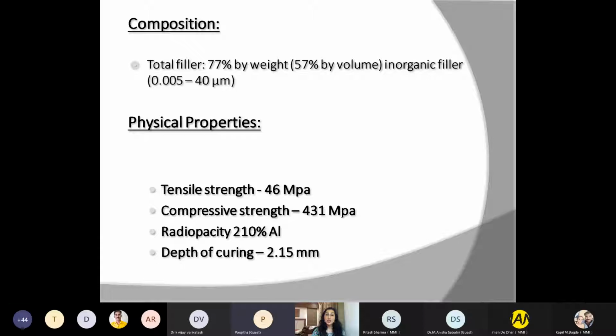The best part is that it is very strong, and you need a flowable that is strong because all the flowables that you have are not strong. Although they are flexible, they don't have strength. This one has a good strength because of the filler content. The tensile strength is 46. The compressive strength goes to 431 MPa, which is quite good.